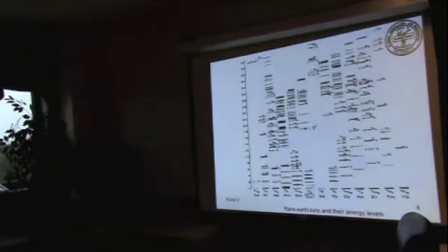And I deal mainly with rare earths. These are the different rare earths, and they all have practical applications. For example, neodymium is used to build a high power laser. Whenever an electron drops down from here to here, it emits 1.06 microns. That's called the Nd:YAG laser. That's one of the high power lasers that for some time people tried using for laser fusion research.